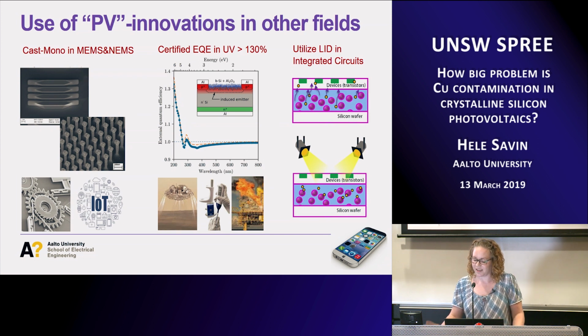And that brings me to my actual topic of copper. Now we're talking about integrated circuits and microelectronics, which really require high purity silicon and high purity clean rooms. Everything must be on a different level than in photovoltaics. But there they still today have a problem with small copper contamination. Copper is indeed a very nasty impurity because it's known to diffuse at room temperature, and it's very difficult to measure. But it's known that eventually, when you make your transistors and devices, it will find its way to the devices, which will then be destroyed.